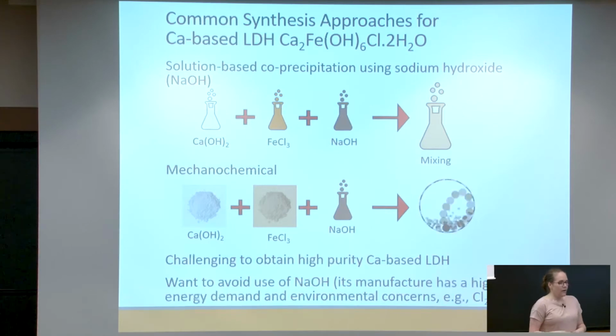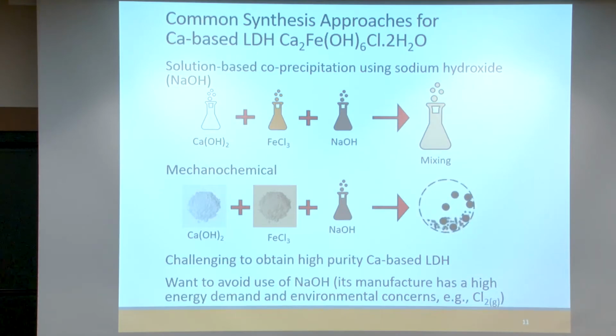So with these two approaches, it's somewhat challenging to obtain high purity calcium-based layered double hydroxide, mainly because there's a lot of secondary phases that tend to form. And so this is one of the challenges that we've been trying to address, is how can we just obtain the layered double hydroxide itself.